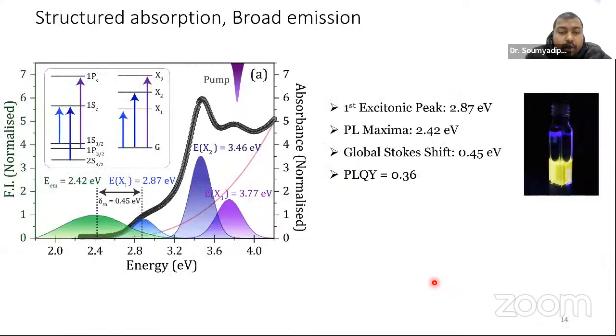Next, you can see the fluorescence, the emission of the quantum dots. Although it looks yellow, it's basically greenish yellow. The emission is around 515 nanometers. This is the absorption spectrum of the quantum dot, which has three peaks that can be ascribed to the band transitions. The first peak at 2.87 is due to ground state to X1, and the other peaks are for higher excited state absorption.